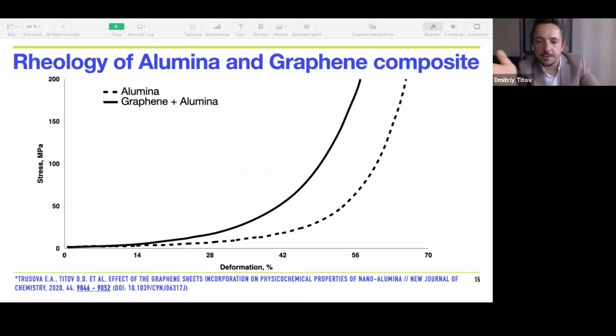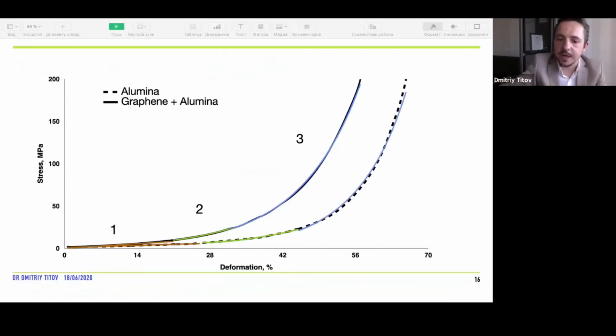Here you can see a typical deformation-stress curve based on 5 independent experiments for both powders. Using mathematical apparatus, we can divide the curves into three steps. The first one is a linear section, the second polynomial, and the third exponential. Since the alumina particles have a nanoscale size, it becomes energetically beneficial that the shape becomes close to spherical. So the first stage of the rheology curves is limited to a deformation value of up to 20-27% and is accompanied by a linear increase in stress and deformation, which occurs due to the powder particles moving into the pores. Here, the process obeys Hooke's law of elastic deformation.